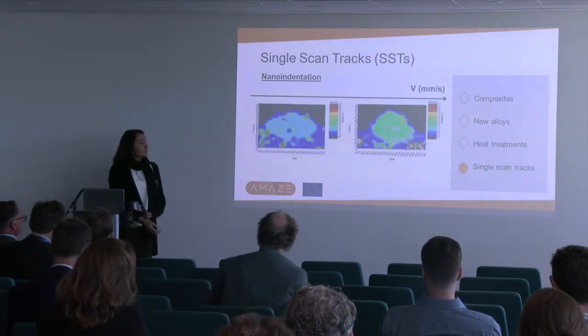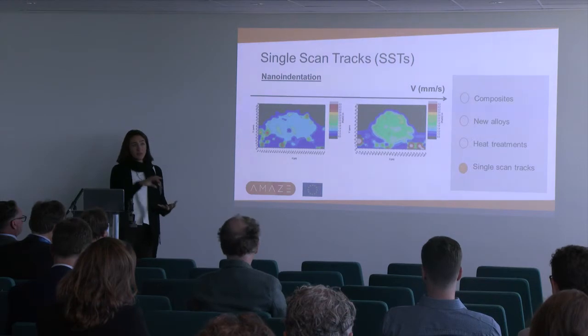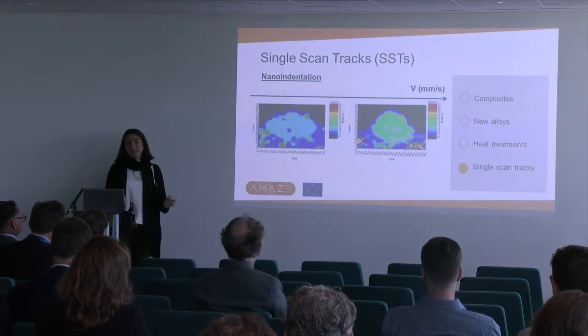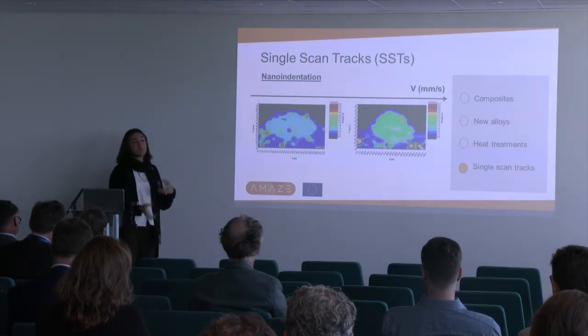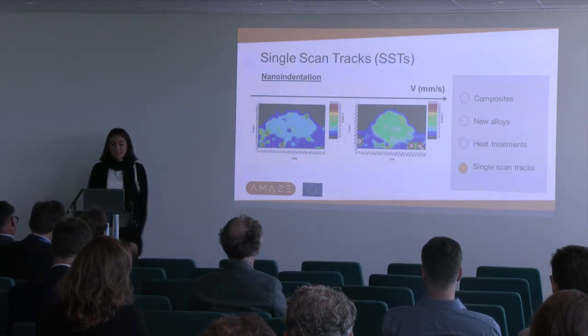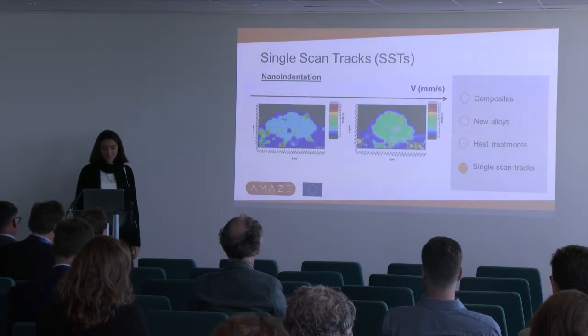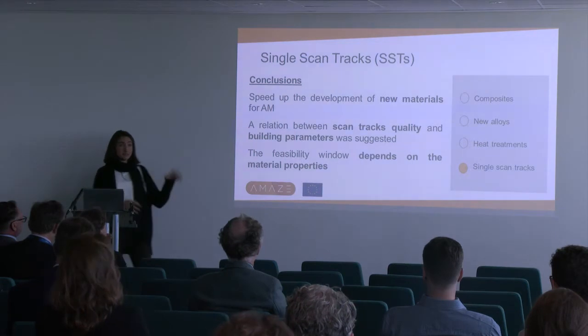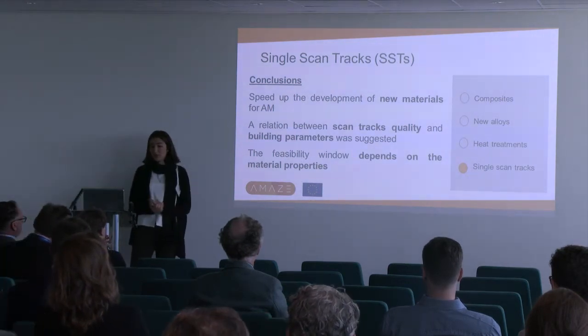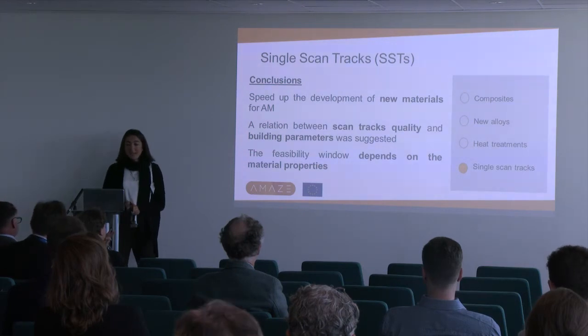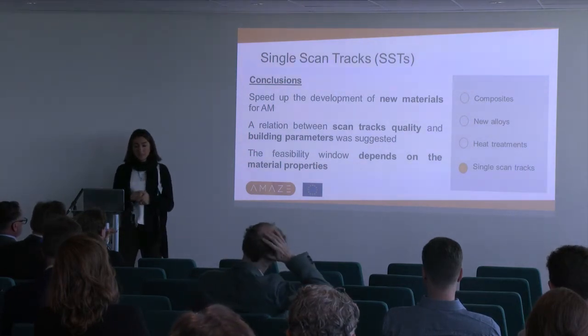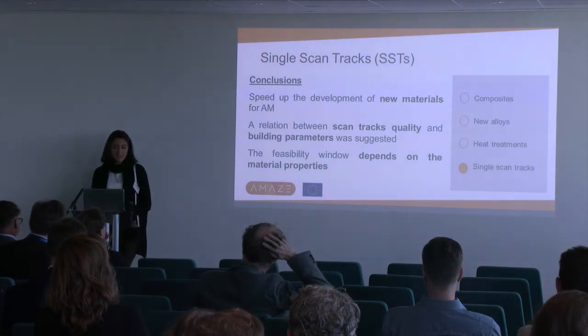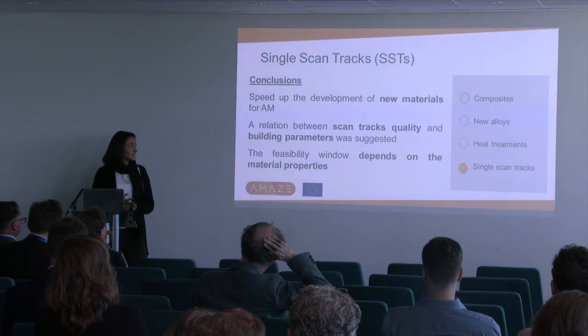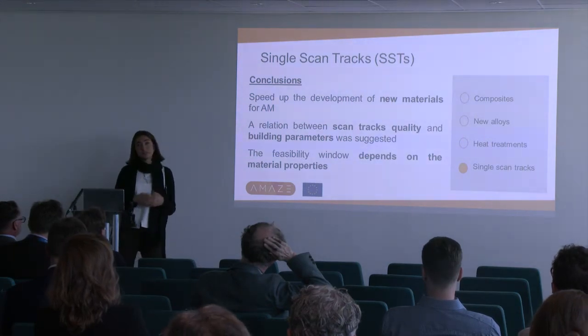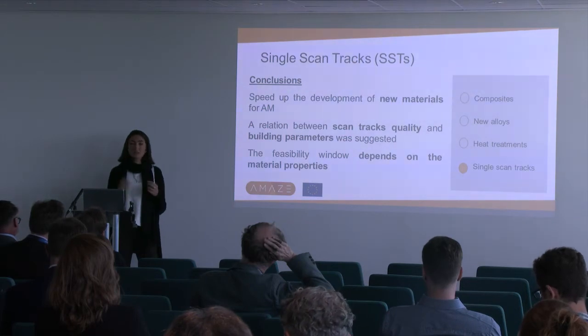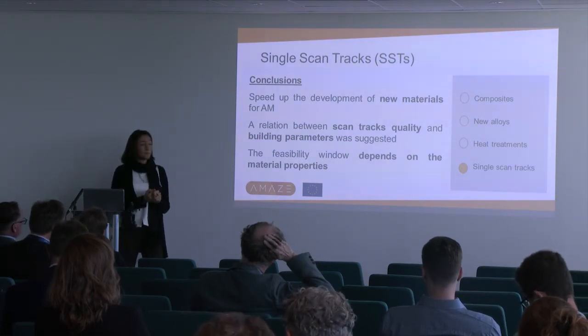What we wanted to do was to see the effect of the building parameters, so only of power and scan speed, on the nano mechanical properties of the single scan tracks. And so we could find some interesting correlations between parameters and nano hardness. As a conclusion, this method, the single scan track, can speed up the development of new materials for powder bed AM. With this study, we could find a correlation between building parameters and scan track quality and stability. We also observed that the feasibility window, so the process window, strongly depends on the powder properties.